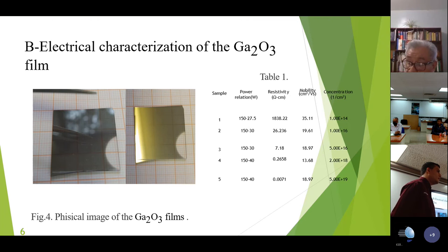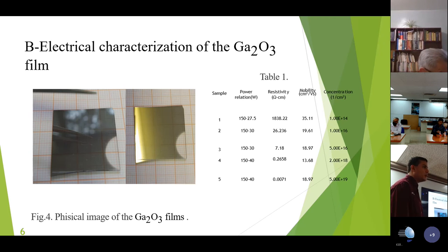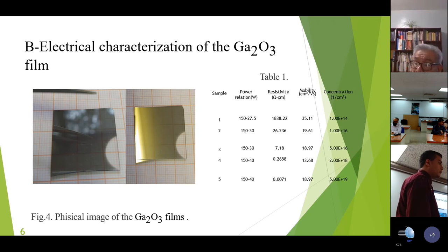I can see a clear trend of the resistivity. If you increase the power, the resistivity decreases. It's a clear trend. Why not use a higher power, in order to follow the trend? Well, in this current research, we had some results with limited powers. We need to measure at least something, because at some power, at the moment, with a relationship of 150 to 40, we stop seeing any value. And so we increase the relationship of powers, then we obtain values.